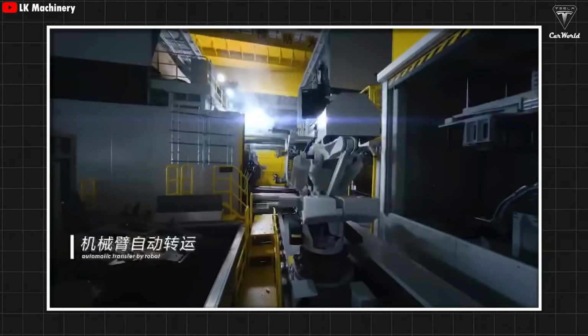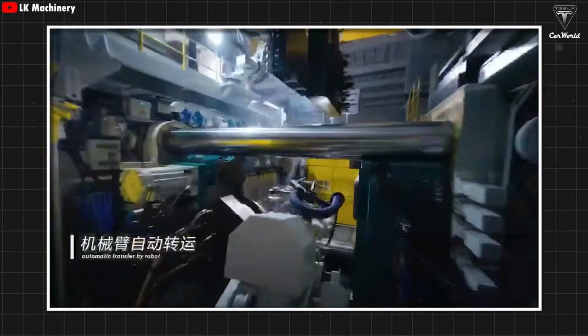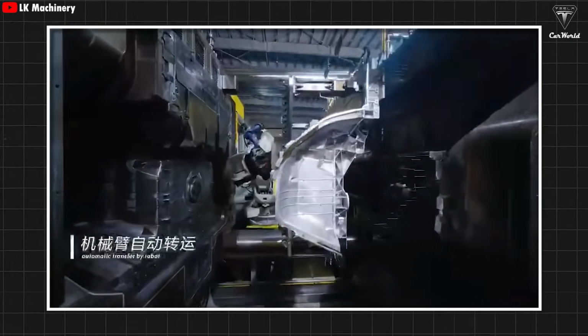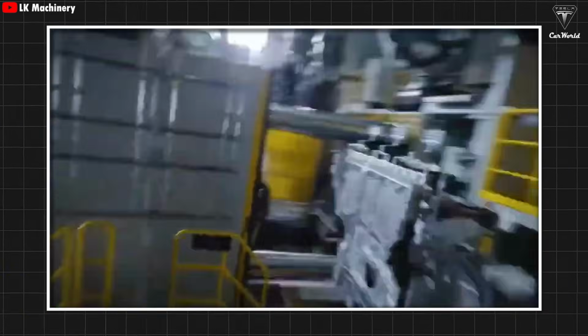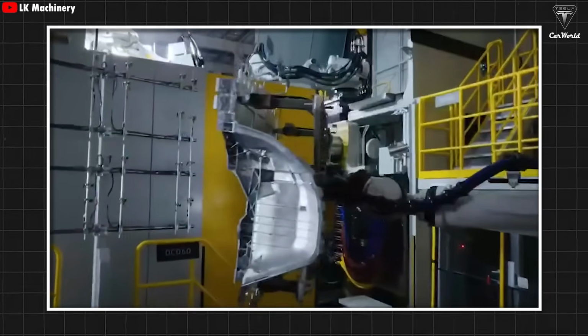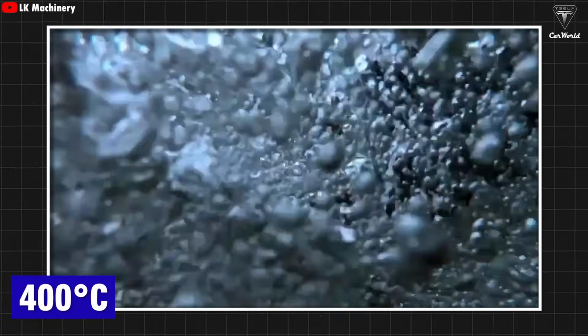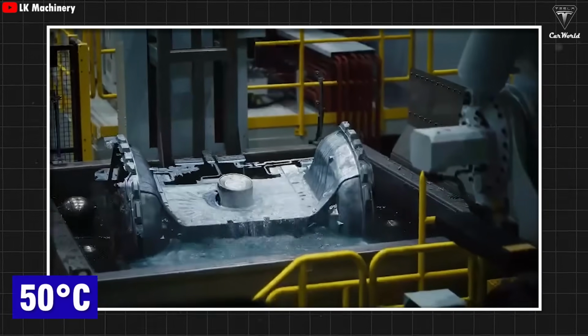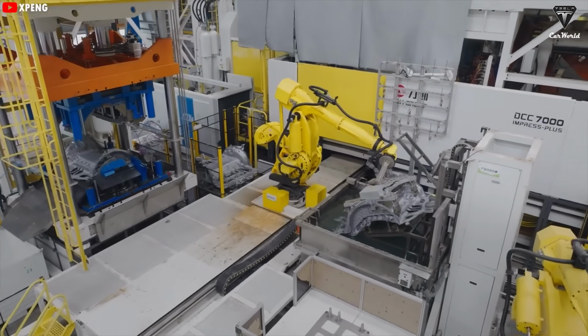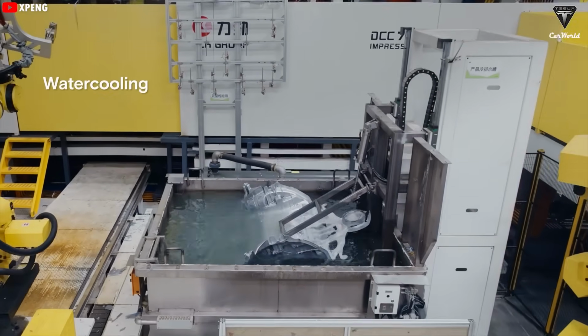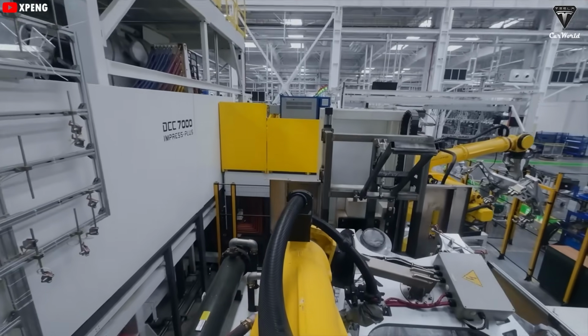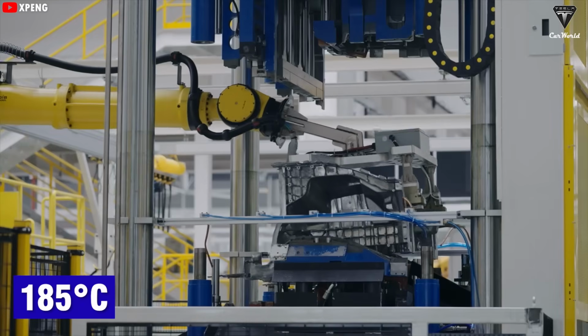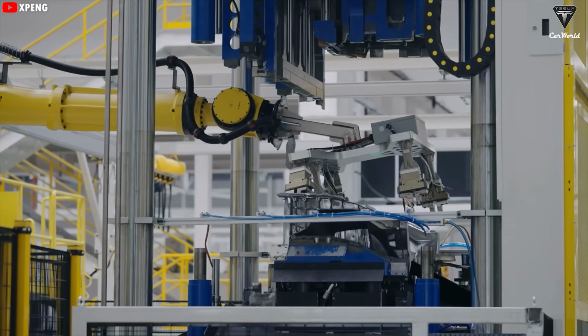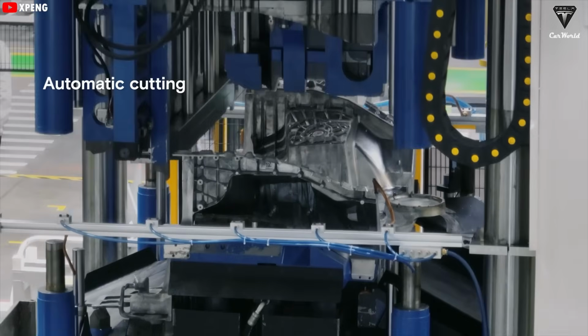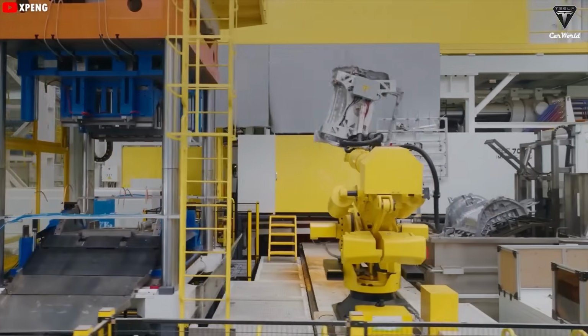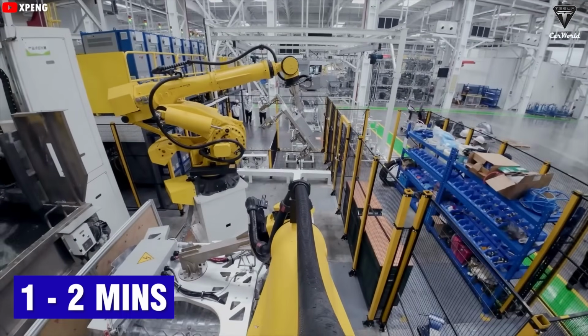After the aluminum is injected, it remains in the mold until it solidifies. The cast part is removed from the mold at around 400 degrees Celsius. It's then placed in a cooling tank to rapidly bring its temperature down from 400 degrees Celsius to about 50 degrees Celsius. This quick cooling helps eliminate certain defects and improves the material properties. Finally, the mold is opened, cooled to around 185 degrees Celsius, and thoroughly cleaned by a robot to prepare for the next cycle. The next casting cycle typically begins 1 to 2 minutes after the current one ends.